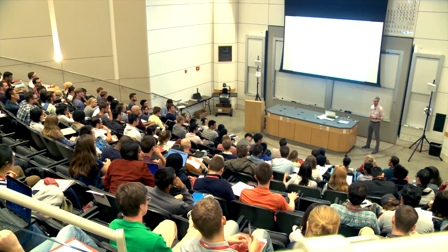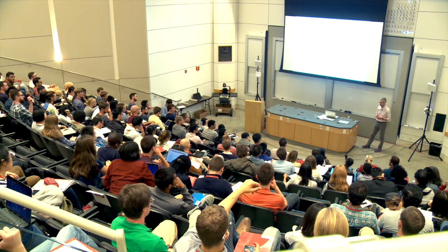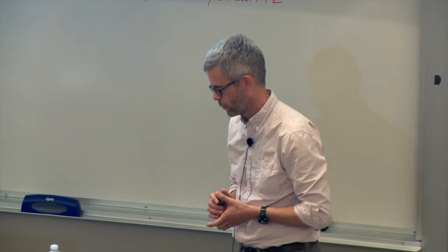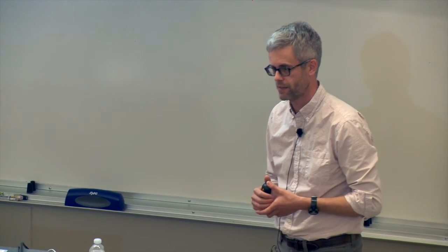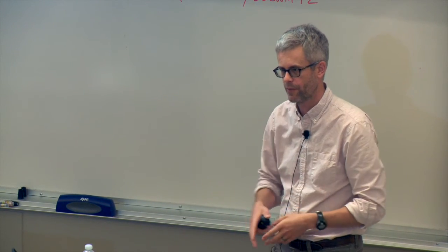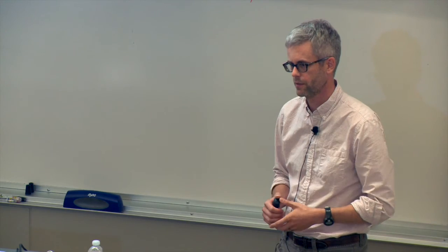Can you give an idea of the relative production cost that you'd expect for this type of cell versus your silicon cell? Is it going to be much, much cheaper to produce, or what's the relative cost? So if we choose to just make perovskite panels, not as tandems, we think we know what they're going to cost. We partnered with Mike Woodhouse at the National Renewable Energy Lab, who runs a team that does cost modeling. He's projecting silicon is going to go down to about 40 cent per watt, and he thinks we could get to 34 cent per watt. So a little cheaper, not massively cheaper, just a little bit.